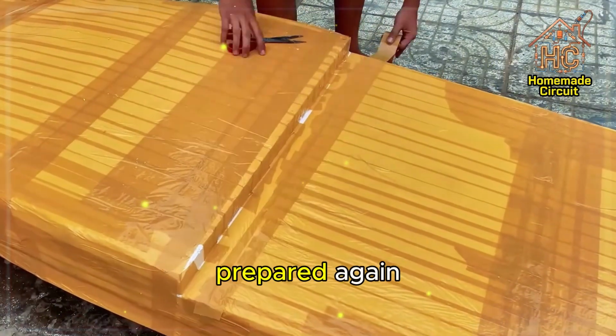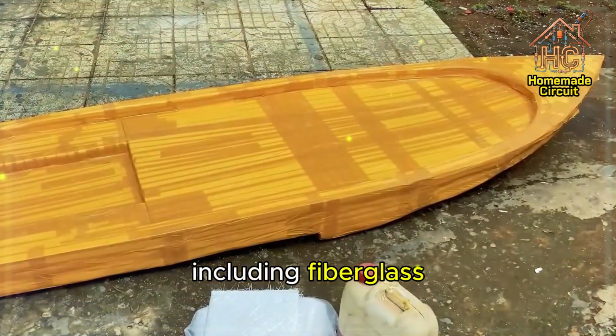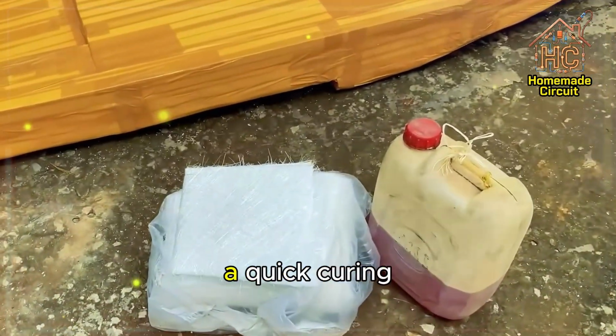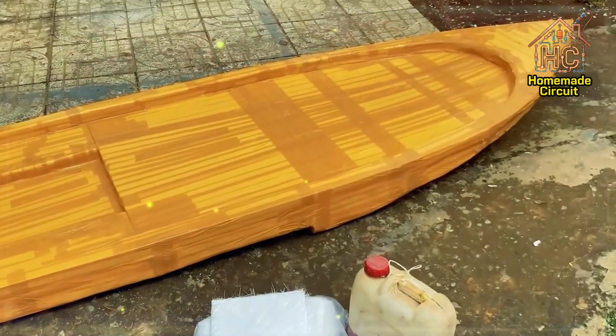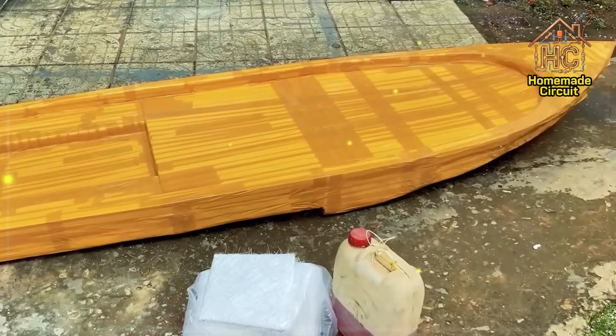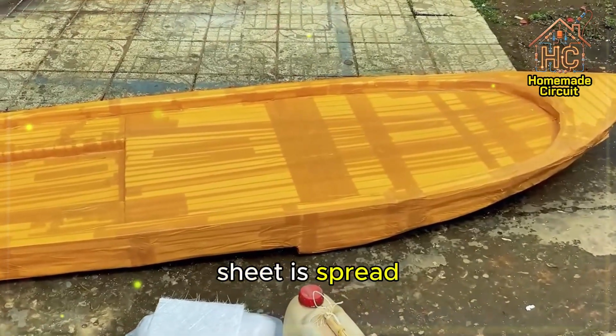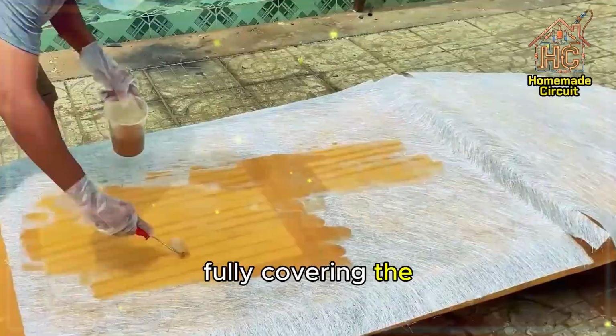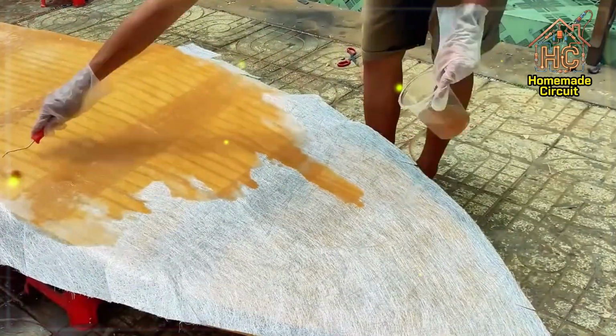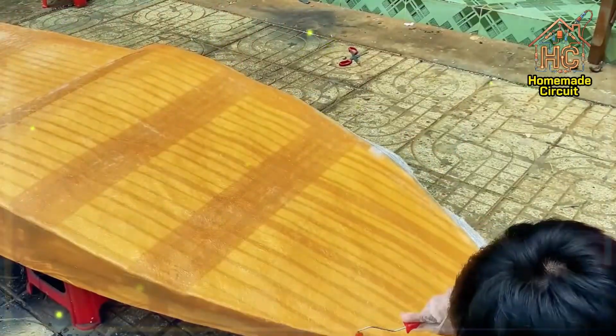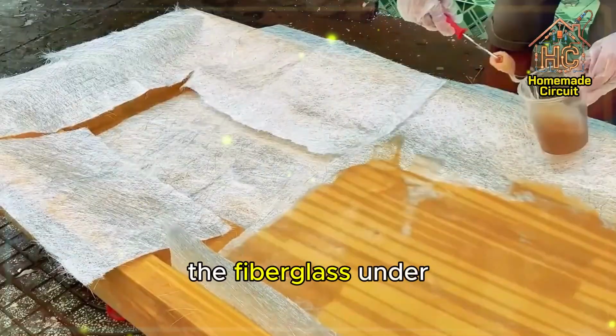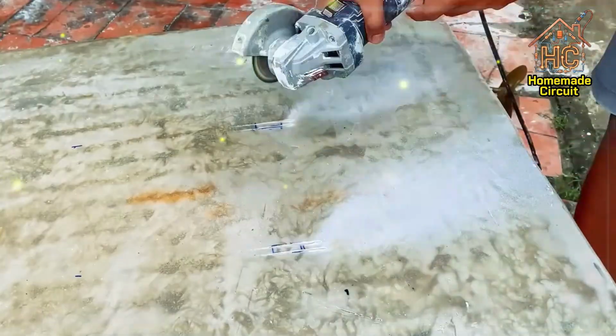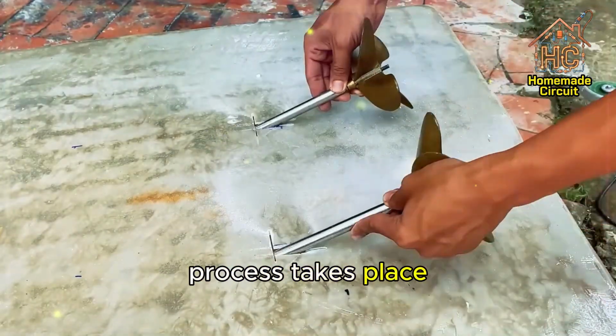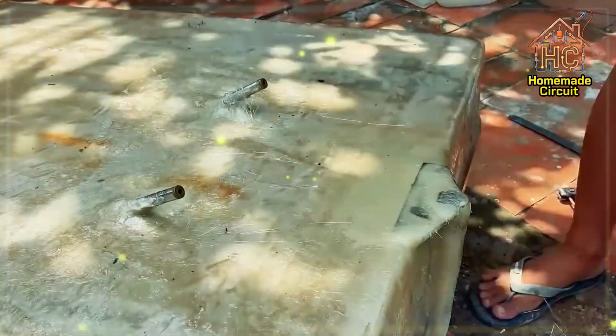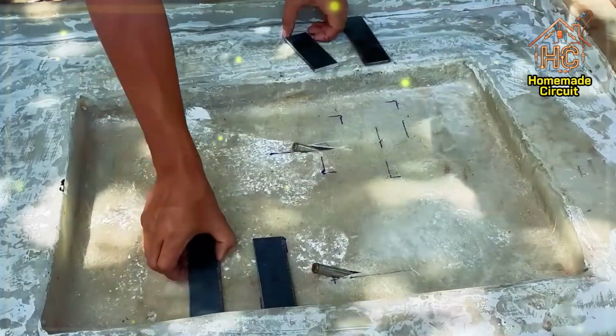Composite materials are prepared again, including fiberglass, polyester resin, and a quick curing catalyst. A large fiberglass sheet is spread evenly, fully covering the foam mold surface sealed with tape. Liquid resin saturates the fiberglass under the roller, squeezing out air bubbles as the molding process takes place. The composite shell is completely cured.